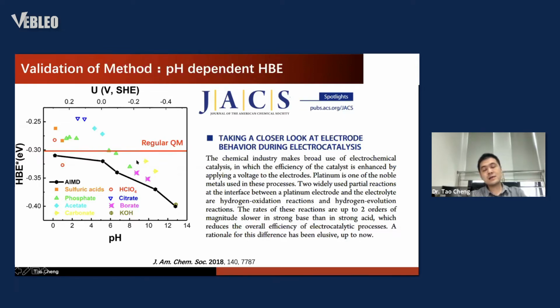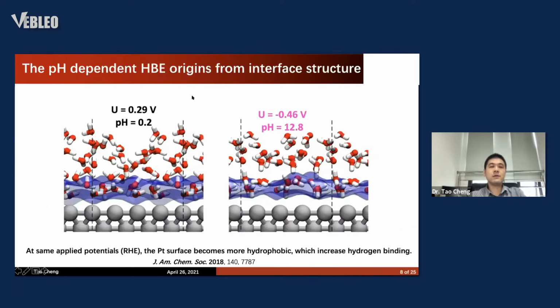But using the simulation methods we developed, we can now see that the black one can well capture the experimental trend, both qualitatively and quantitatively. This work has been highlighted by the JACS Spotlights. Then, if we look into the microstructures, we can explain the hydrogen binding energy dependence on the pH from the interface structure. What we show here is a comparison of the structure at low pH, 0.2, and at high pH, 12.8.